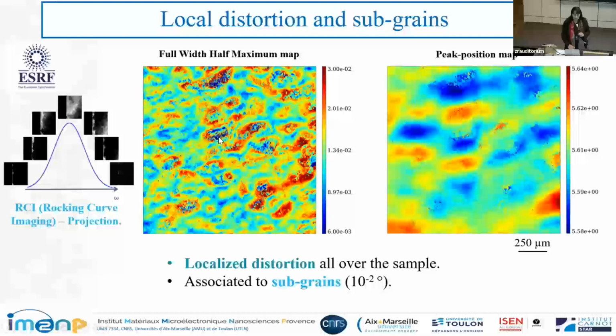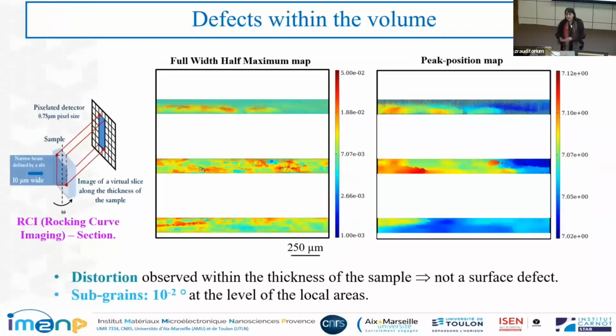And in fact, they are characterized by localized distortion all over the sample, but as well subgrains, as can be seen on the peak position map. We wanted to know if this is only a surface defect, because we project our images during solidification, but with rocking curve imaging, you can also use a variation using slits. But here you have 3 slits that project what you have within the thickness of the sample. So the entrance face is here and the exit surface is here. And what you see is that we find again the same type of defects, and we measure exactly the same value for the misorientation. And this is not a surface defect.